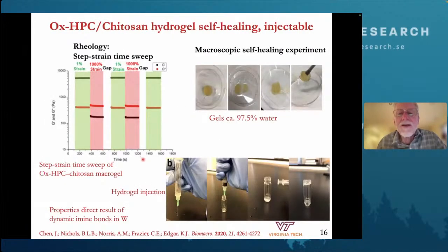And these hydrogels have some interesting properties. So we can look at it rheologically, and what we see is that at low strain, we have this arrangement of G prime and G double prime. As soon as we apply some strain, they switch - we liquefy the hydrogel. As soon as we take that strain away, it goes right back to where it was before. And we can repeat this over and over again.